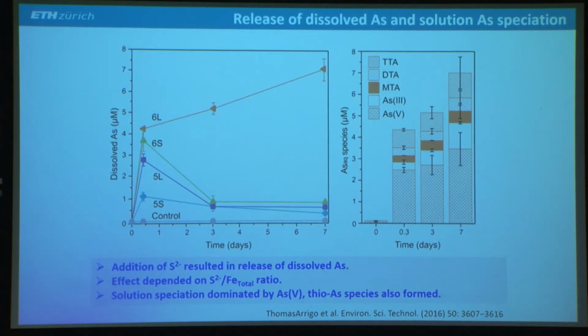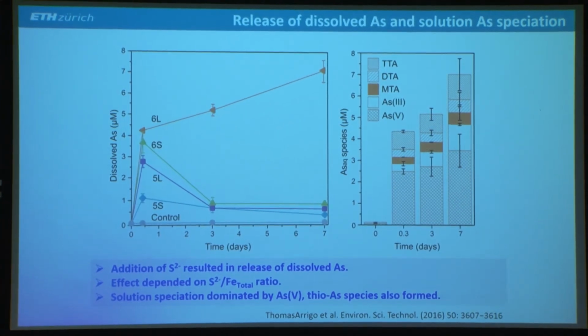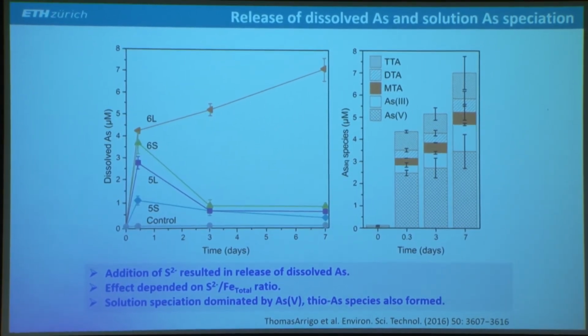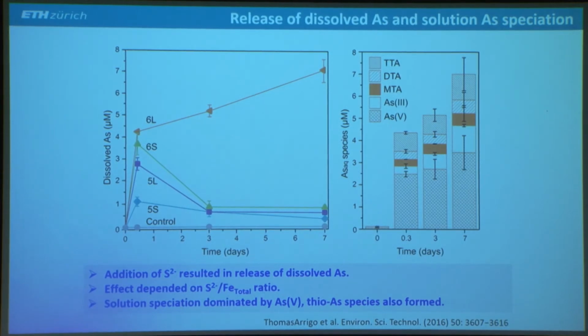And this can be quite important because these thioarsenate species are known to adsorb a lot less to oxide minerals than inorganic arsenic, arsenate and arsenite. And so this might help in part to explain the higher solubility of the arsenic here, but maybe it has also to do with the mackinawite that formed in the other samples.